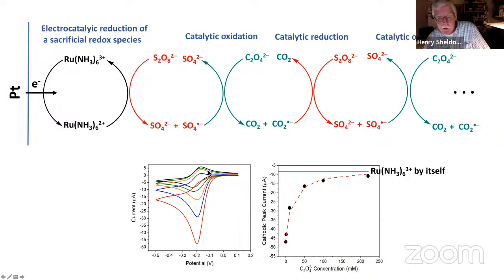It looks reversible. All right, and what's happening here is once I get this thing started, all of the oxalate, all of the persulfate now is being reduced through this chain reaction right here. All this chemistry going on, which could be millions or trillions of electron transfers in the solution, is completely transparent to the electrode. There's no current here associated with the homogeneous chemistry. And all you end up seeing is the reduction of ruthenium hexamine.